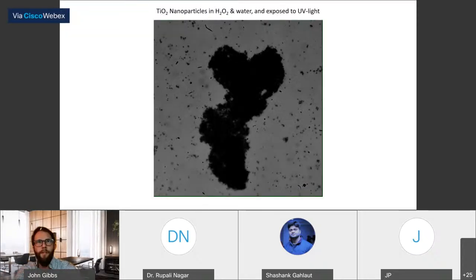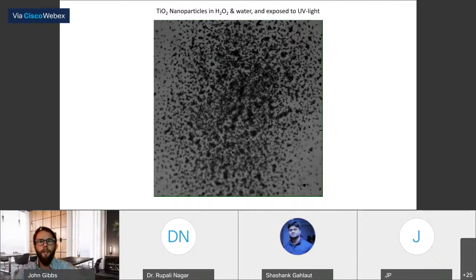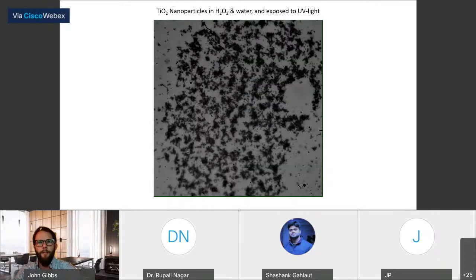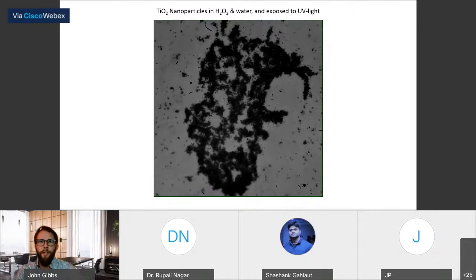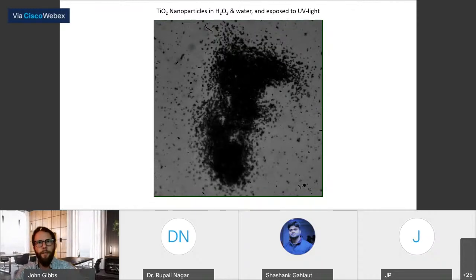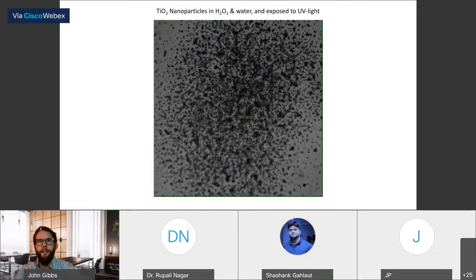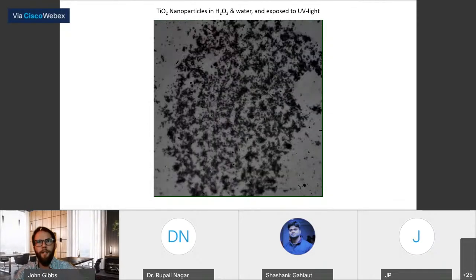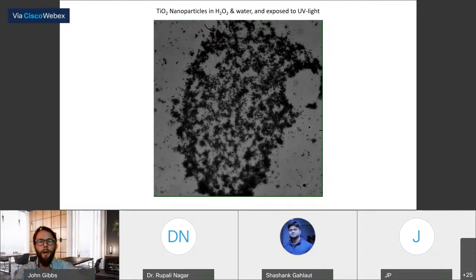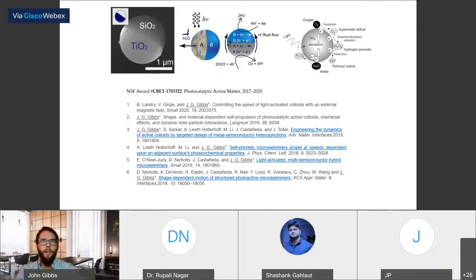This first slide is a very simple experiment. We've taken water and hydrogen peroxide and thrown some titanium dioxide nanoparticles into the solution. What you're seeing here is that the particles come together, but when we turn the ultraviolet light on, they start to move apart. So you see some interesting looking collective behavior. However, you might recognize that the patterns being formed are fairly random. What we want to do is see if we can utilize glancing angle deposition to make this type of behavior a little bit more controlled than what we see here.